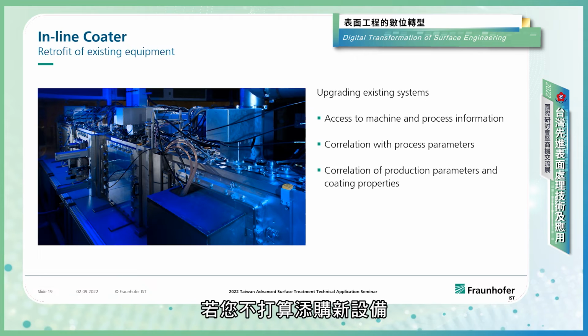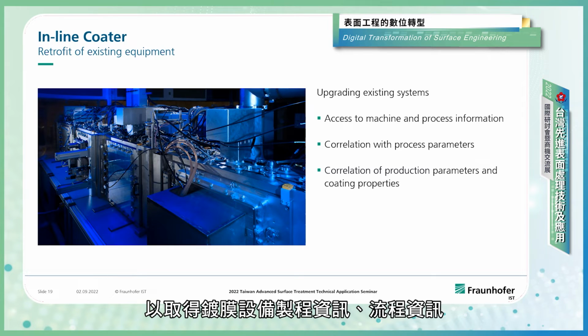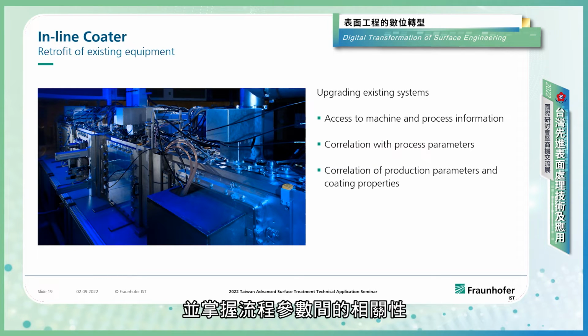If you don't have new equipment that already has all the data, you also can retrofit existing equipment. So like we did with a vacuum coating system that's shown here, we added some sensors, and we want to upgrade the system to get access to machine information, process information, and to get correlations between the process parameters and what's happening with the product, with the coating itself. So we want to correlate the production parameters with the coating properties finally.